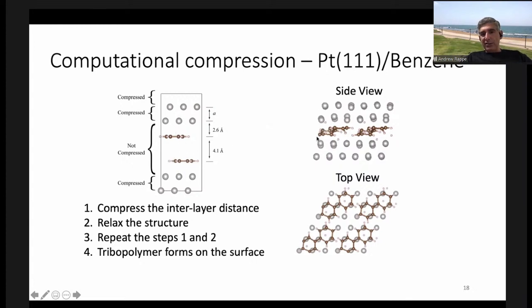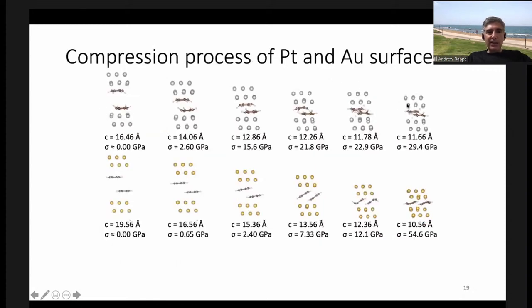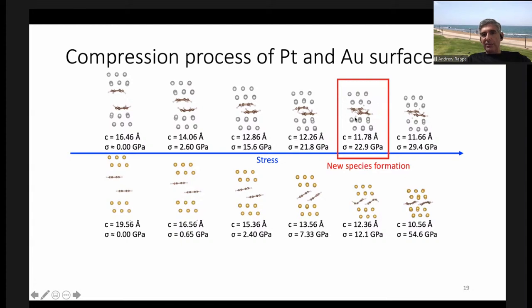And eventually we get to a situation where there's a lot of compression, so much so that the molecules deform and maybe they chemically react. And now I'll show you the next slide where you can see the top row is platinum. We apply more and more stress and we show here it is at equilibrium. The benzenes are sort of bonded to the platinum. You can see them making a cup shape. And then when you apply pressure, they get closer together and closer together. When they get here, this one actually loses a hydrogen and this one loses a hydrogen and the two carbons bond. And so it makes a new biphenyl species.